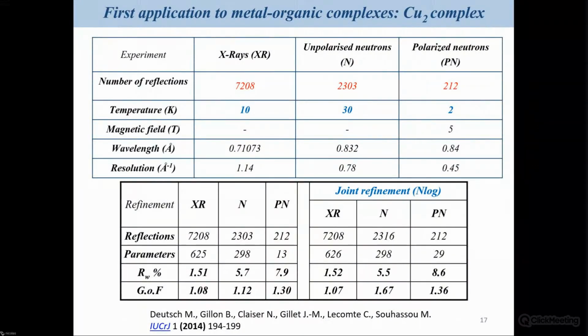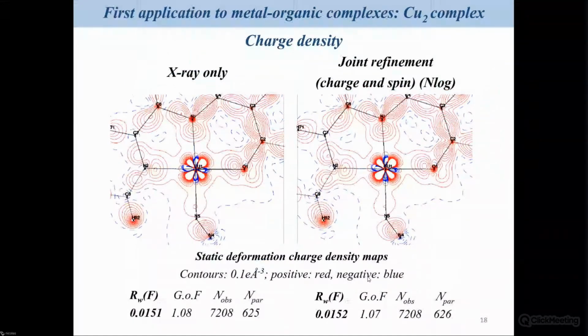And here you can see the results on the left for each dataset treated separately, and on the right, the agreement factors obtained after the joint refinement. And you see that you have something which is very good if you compare each experiment separately, because for the joint refinement, you have agreement factors that are very close to the ones you can obtain for isolated treatment of each dataset, which means that we have something which is very good at the end and very close to previous works.